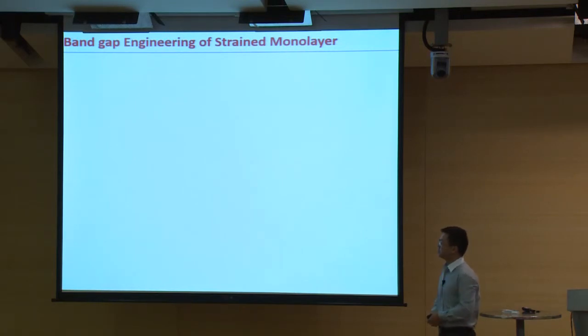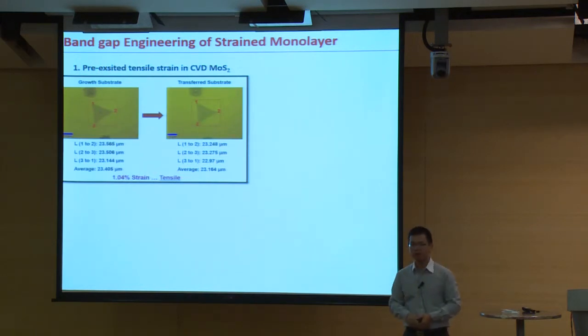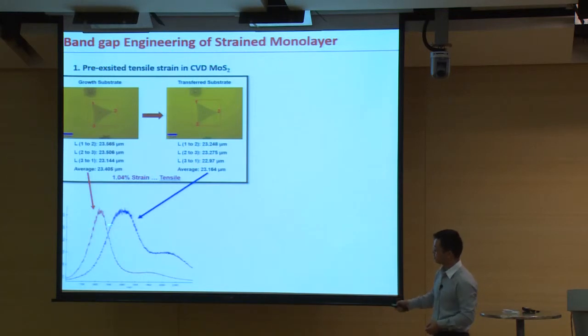All right. The strain-induced band gap tuning is also a very hot topic in these 2 years using the TMD materials. So there I have 2 things to share with you. The first thing is, for CVD molybdenum sulfide, there might be some pre-existing tensile strain in this sample. Okay, this is the as-grown molybdenum sulfide on silicon oxide, and then we transfer them to another silicon oxide. And what we can find is that there is from 0 to 1% tensile strain in the as-grown materials. And the PL spectrum is also different, shifting from the left to the right.